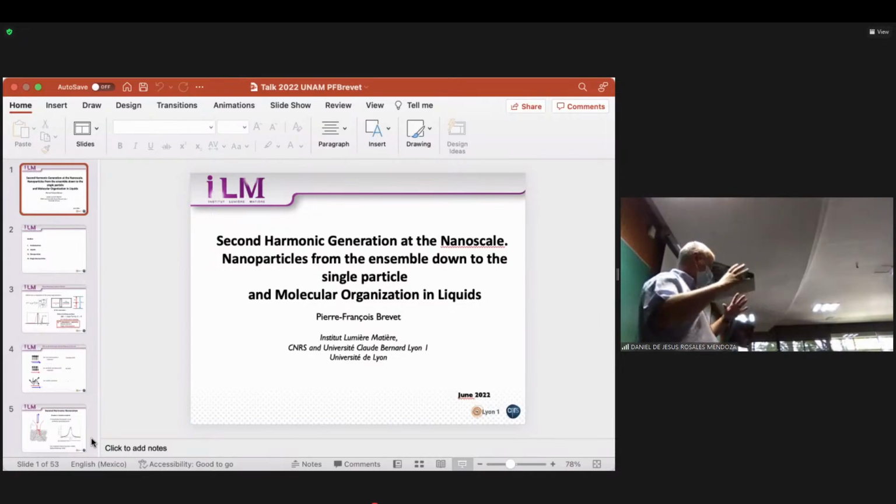But if you get a bigger particle, the resonance broadens, especially on the blue side, and that's due to the quadrupolar surface plasmon resonance. So you see that the quadrupolar resonance is not at the same position. If you switch from this dipolar to quadrupolar response, the polarization plots will change. We have a work on this. So you can tune this with the wavelengths. Thank you. Any other question?